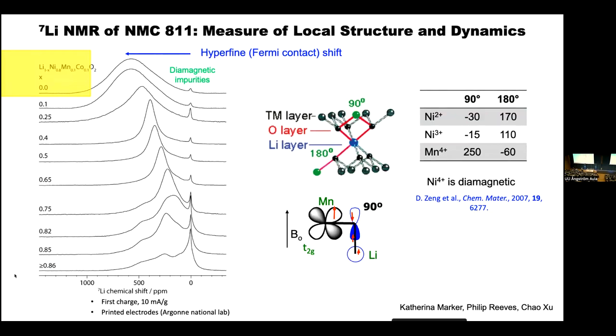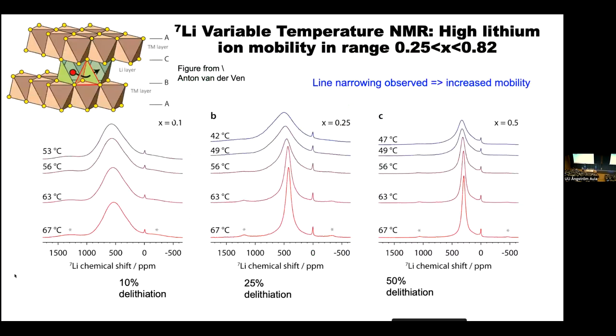At the top, it's mostly nickel 4+, which is a diamagnetic system. And so it becomes simpler because you're just seeing the paramagnetic manganese 4+. The thing that I want to focus on, though, is the middle, where apparently the spectra look a lot simpler. And this is due to something called exchange narrowing, where if the lithium ions are hopping very fast on the NMR timescale, you get an averaging of the broad signal.